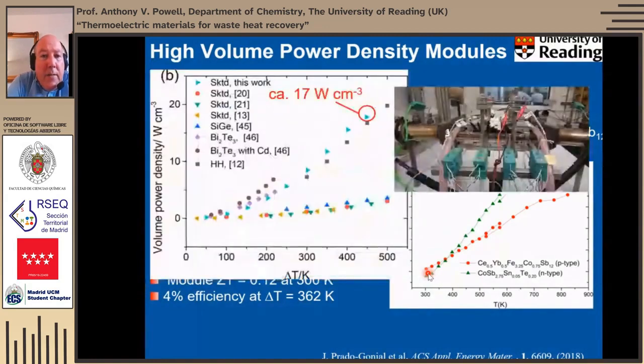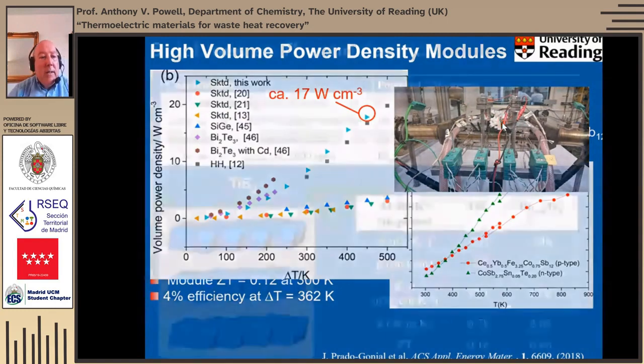And that then gives us something. It produces about 17 watts per cubic centimeter. And these were then tested. For instance, this is a Ford 2-liter engine. These modules were tested on that engine in terms of extracting the waste heat and converting it into electricity. And this generates between 400 and 500 watts. So we can actually start to use materials in real applications.